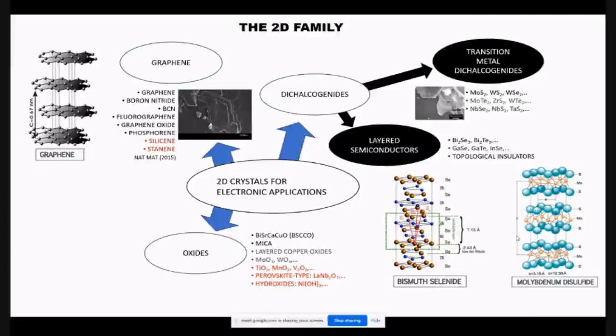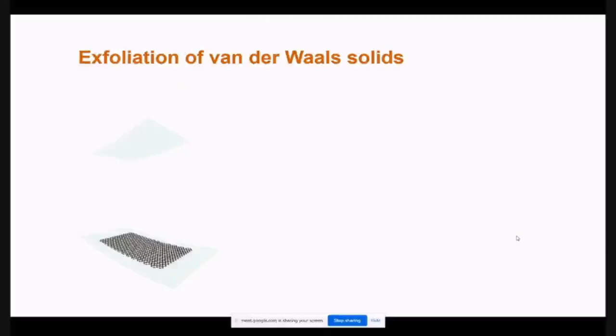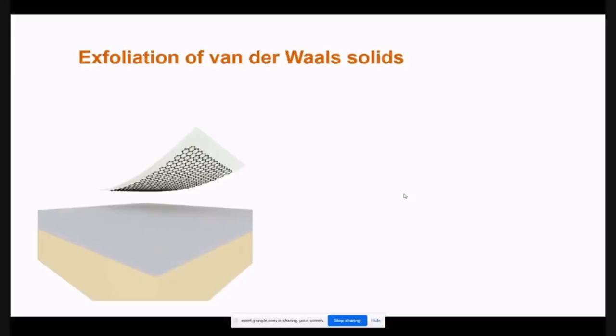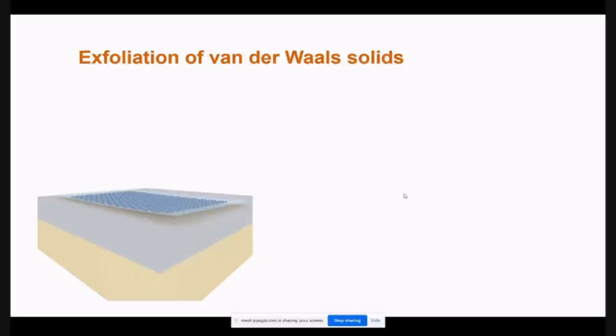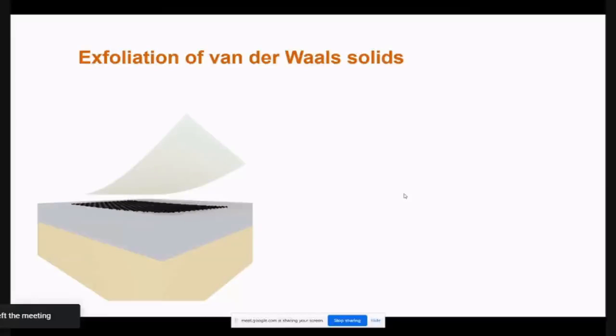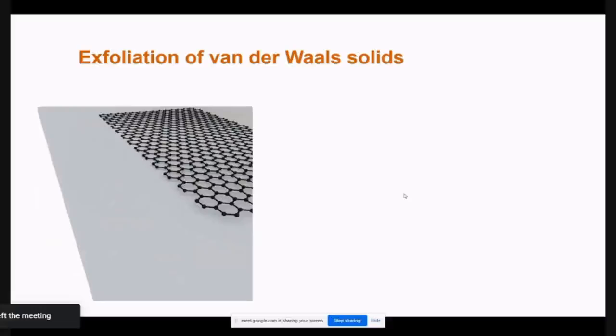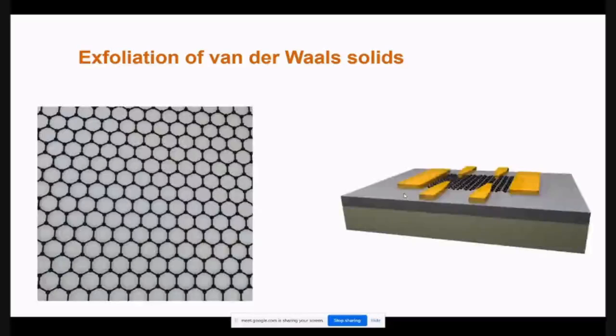Okay, and these numbers are staggering, because even with one, like graphene, the number of properties we can get is massive. And I'm going to show you a little bit of that. So this whole concept of exfoliation is the reason why we could get this system of layers on a substrate. Usually these are silicon oxide substrates, and once those are created and you use scotch tape to stabilize, and this is a very well-known technique now, one can make devices by putting electrical contacts. And this is how a typical device looks like.